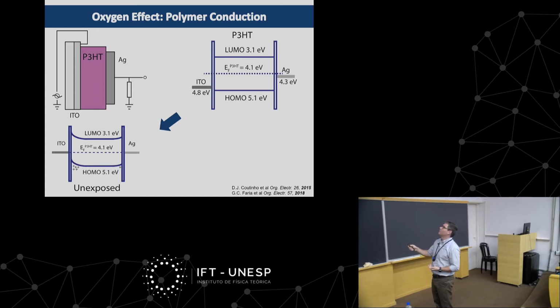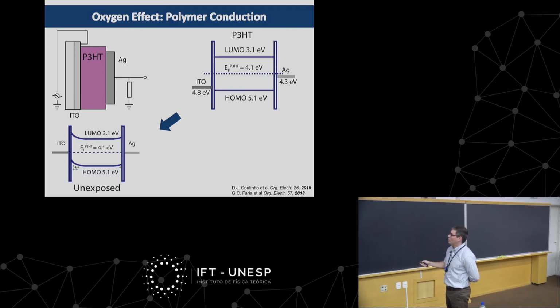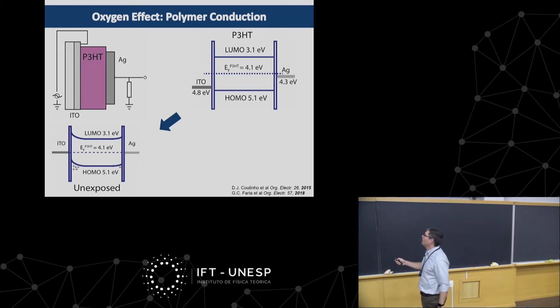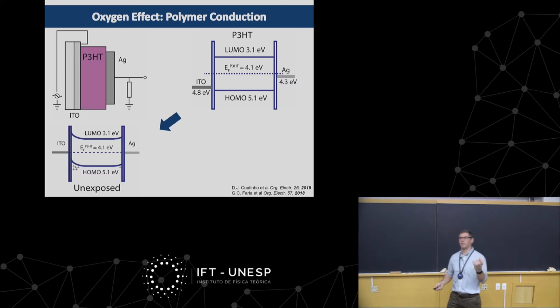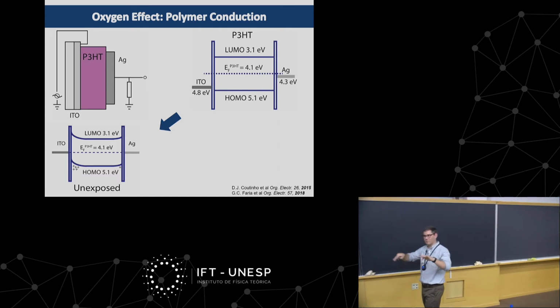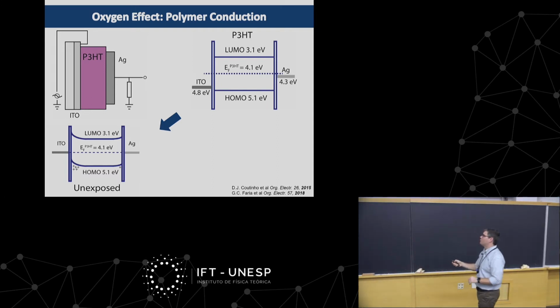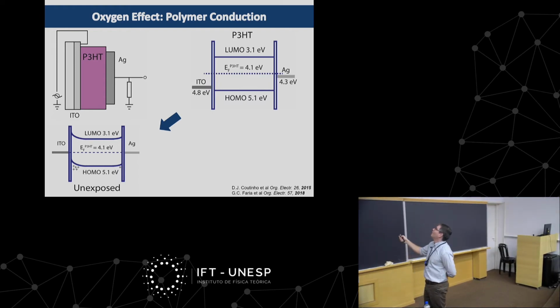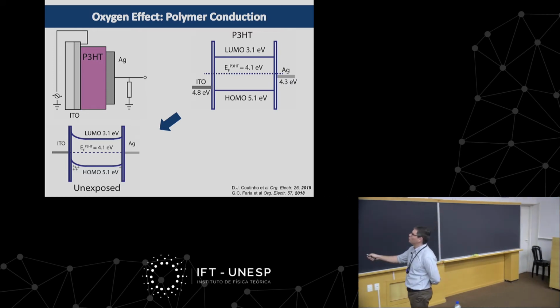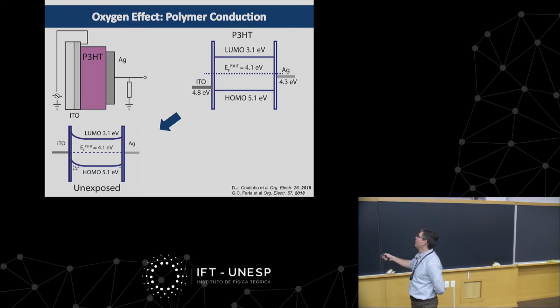And what happens, instead of this static figure that I've shown you before, the realistic one is like this. So the HOMO of the material is actually tilted at the interface in order to match the work function of ITO. And the way nature does this is by ITO injecting charges at the interface, creating this reservoir of charges at the interface in order for the thermodynamic equilibrium of those two interfaces to be equalized. Of course, I have a slight difference between the Fermi level of P3HT, which is 4.1, and the work function of silver, which is 4.3. But this is very small compared to the 0.7 electron volts at the ITO interface. So you do have a little bit of charge on that particular interface, but not as much as on that one.